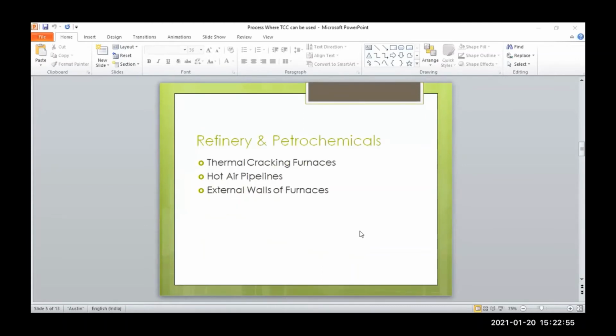Then refinery and petrochemicals. We have already done one project with HPCL in 2005, and it was a thermal cracking process. The quantum of energy saving was around 2.5%, and that amounted to 1 lakh rupees saving per day. The project cost was around 30 lakh rupees at that time, and the ROI came down to 30 days. These thermal cracking furnaces are very huge in size, and have huge potential to save energy. Then there are hot air pipelines. External walls of furnaces can also be applied with our low temperature coatings.